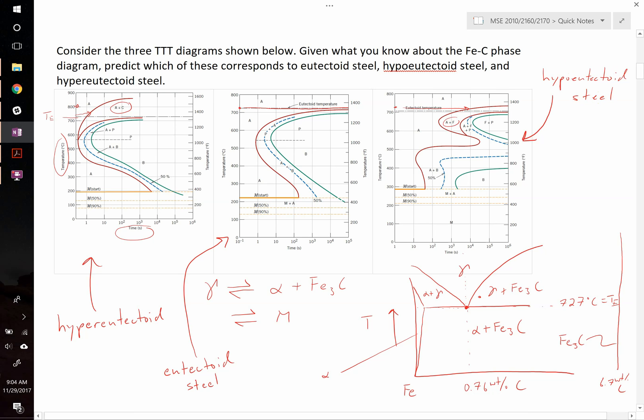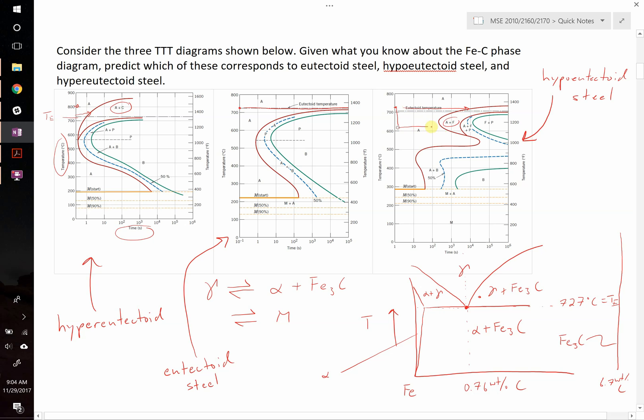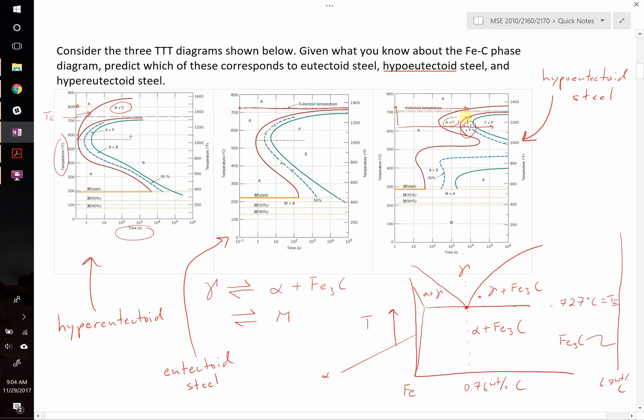Does this all make sense? For example, if we cool the hypo-eutectoid steel down a little and do some heat treatment — hold it there — first it's going to form a mixture of austenite and ferrite. Then in this region you've got a mixture of austenite not yet transformed, your pro-eutectoid ferrite, and pearlite. As the austenite is consumed, it forms pearlite. In the end, you're left with ferrite plus pearlite — the pro-eutectoid ferrite remains on the grain boundaries, and everywhere you had austenite is converted to pearlite.